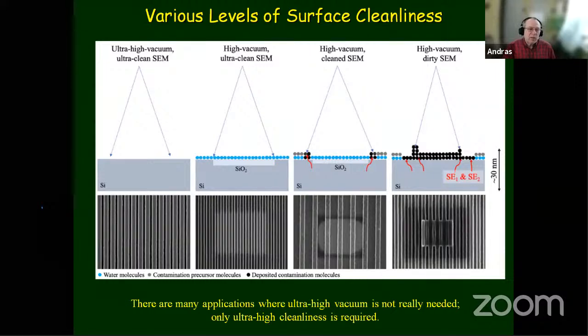Here is a little idea of what we mean by that. If you have high vacuum and a dirty SEM with a dirty sample, you will have that ugly deposition that you can see on the right. Even just one image can get darker and so on. If the SEM is cleaner, but the sample is not really clean yet, then you still have something. The center may stay clean because the electron cleaning and deposition can overwhelm each other.